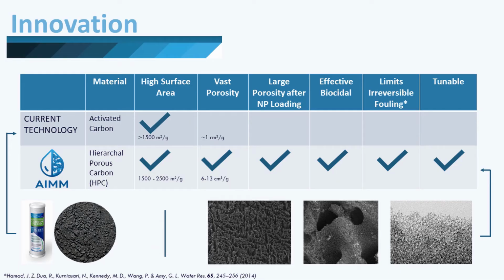The innovative heart of the system is AIMM's Tunable Hierarchically Porous Carbon Materials Platform, or HPCs. This is worlds different than your standard activated carbon found in most water treatment devices, such as a Brita pitcher. Though our HPCs have high surface area, if not more, than typical activated carbon, it's also vastly more tunable as far as pore size, morphology, functional groups, and at the same time has massively more porosity compared to activated carbon.